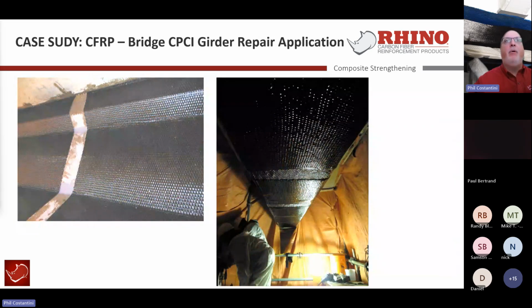Here's a classic example. Does anybody know why we left that opening space between all the U-wraps after the concrete was poured? I'll explain why. The reason that opening was left there is because this is around the area where we introduced the new concrete pour, where we broke everything open, fixed all the reinforcing and reformed it. We allowed that opening to allow the concrete to continue to cure or dry out.